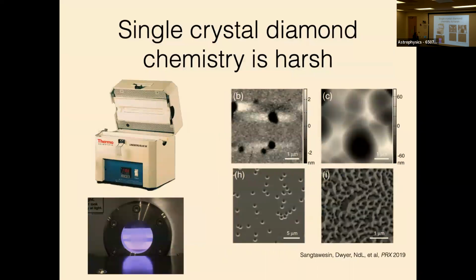Okay, so the challenge here is that single crystal diamond chemistry is very, very harsh. Diamond is inert, it has a very tight lattice. Diamonds are forever, whatever. Normally, if you just stick it in some solution, the solution is not going to do anything to the diamond at all. So the way that people functionalize diamond usually involves things like high temperature thermal processing, sometimes even at high pressures, and plasma. And these things can be quite damaging, as we have painstakingly cataloged in the past. So in general, it's hard to make this compatible with very coherent shallow NV centers, but more importantly, this really limits the scope of things that you can attach onto the surface. It's very difficult to imagine a protein surviving something that glows.